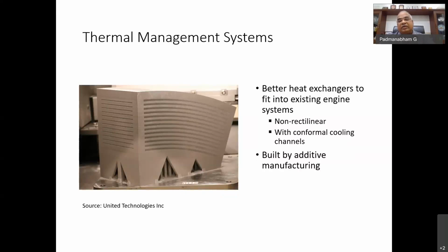And we talked about the very fine channels that we can create inside the components. So effective thermal management systems, like a heat exchanger with a very odd shape. What you are seeing here is not a typical cuboid or something like that, which we usually see in our engineering components. You can see a small segment with different features in it, curved, non-linear features, with conformal cooling channels in it, built by additive manufacturing. So this gives you an idea of the flexibility.